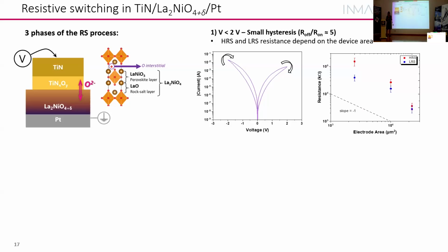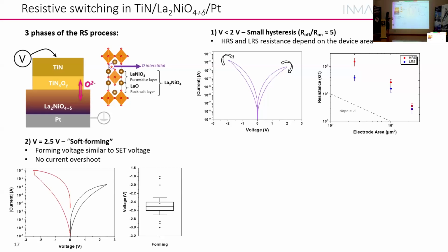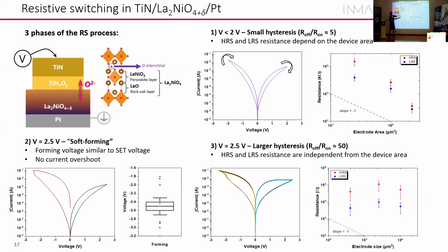What happens if in the same device we apply a higher voltage? So we do what we call soft forming. We create a filament in our device, and then we can have a much larger ratio, so we pass from 5 to 50 in the high to low resistance ratio. And now we do not have an area dependence anymore. As it's a filament that is connecting, the high and low resistance states are independent of the electrode size.